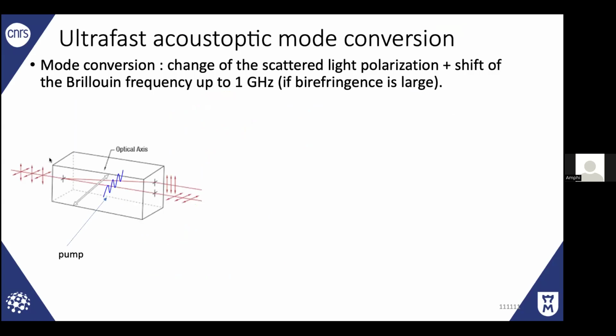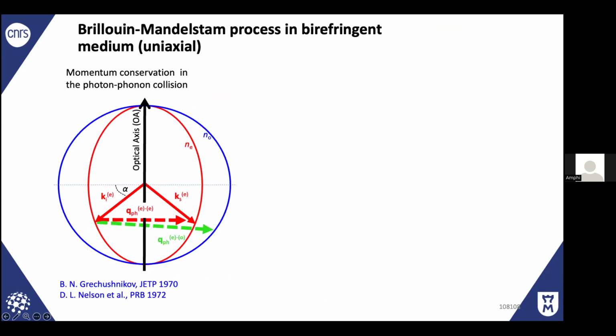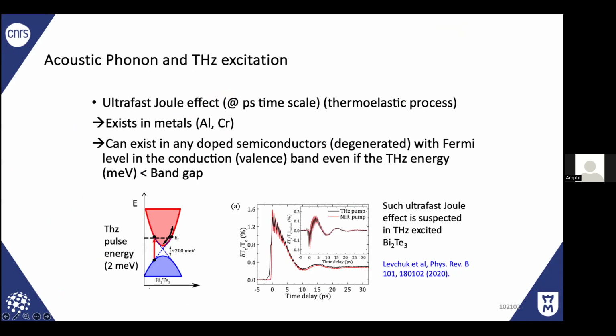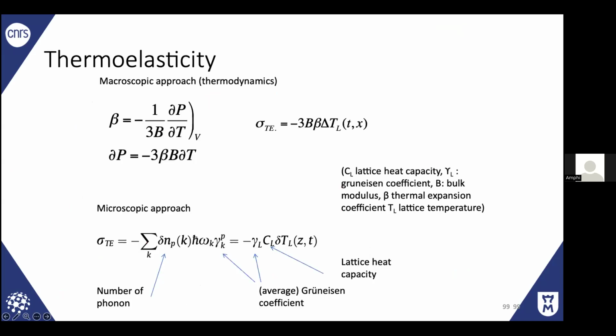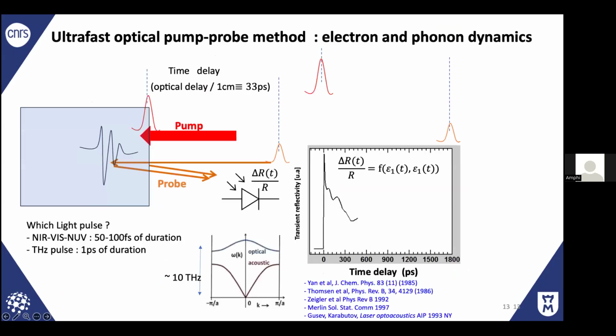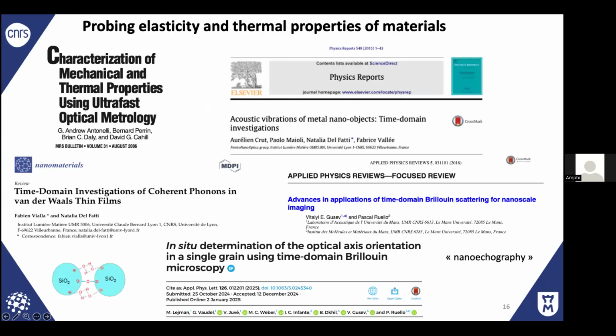Maybe it's easier to shift directly to the slide. There is a review I mentioned in the beginning by Fabien Viala. If you're interested, they look at van der Waals films. Basically with that pump probe experiment, they induce film ringing, and by looking at the vibration frequency, they can come back to the bond stiffness, the nature of the interaction between the 2D materials and the substrate.